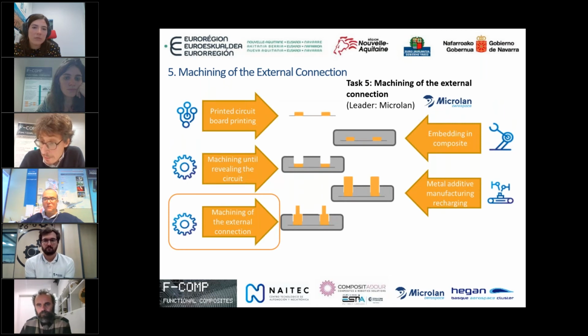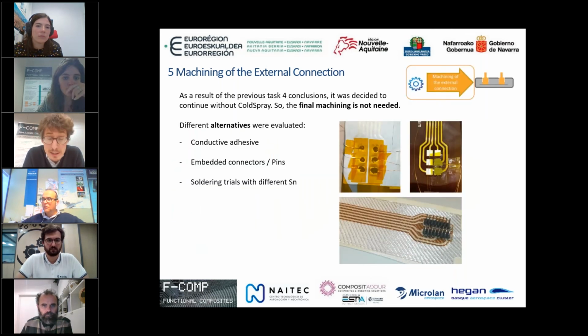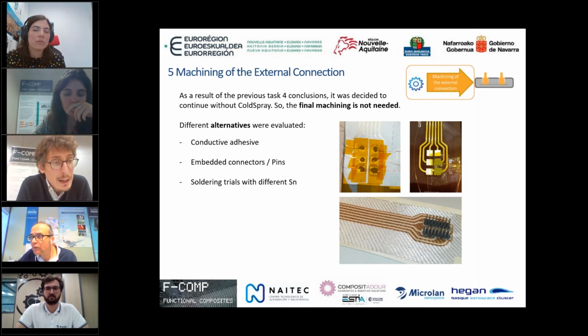This gives a problem for the next step, the machining of the external connection. In principle this task was part of the MICROLAN part, but instead we looked for alternatives for putting the connectors. We tried to find a proper conductive adhesive that could be applied and withstand the high temperatures later in the curing process of the composite. We tried different kinds of soldering as well, but the temperature is 180 degrees in the oven, so we cannot use the typical, more easily accessed soldering. We used solderings with very high melting points, but the solution was not very good, because of the very thin substrate laminate that we have.